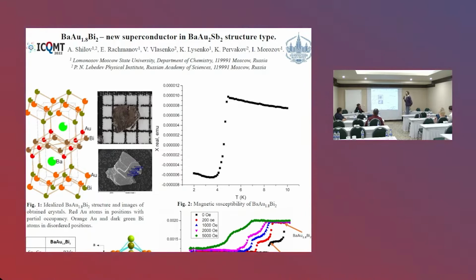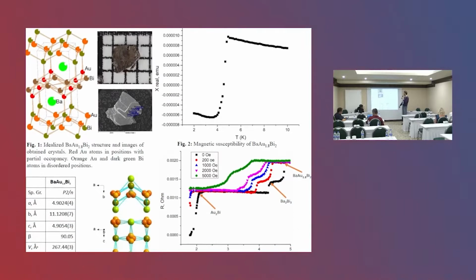My short talk today will be an extension of Igor Morozov's lecture that was this Wednesday. In our work, we tried to get new layered bismuthides, and we discovered a new superconductor in the barium gold 2 antimony 2 structure type. Can you scroll a bit down, please? We also found that this structure type is probably described wrongly in the literature; we were able to refine its space group and also found a disordering in one of the layers, which wasn't reported before.